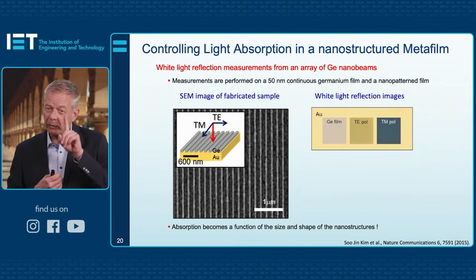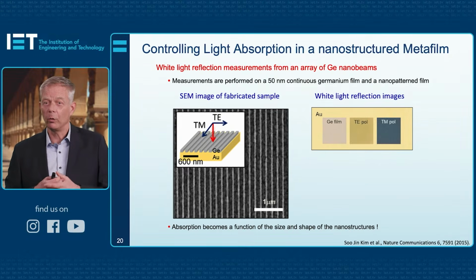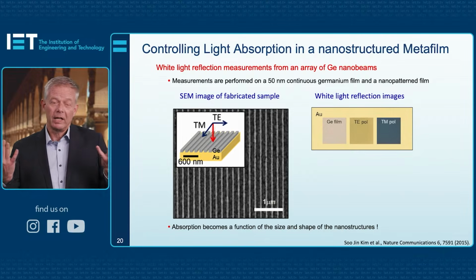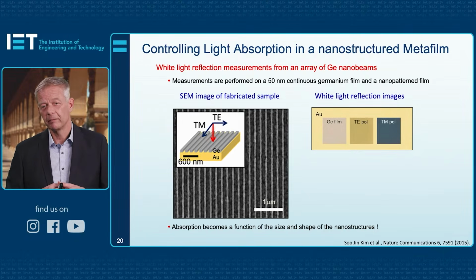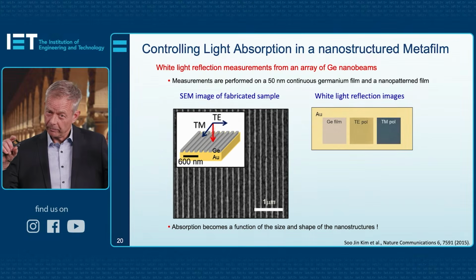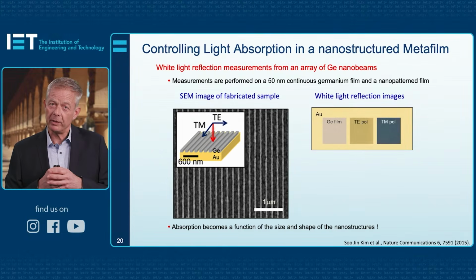But on the right, when we align the electric field along the wires, something spectacular happens. We drive a resonance, and actually the film goes black. So note that in going from the continuous film, by removing about two-thirds of the material, we achieve more absorption. It goes from grayish for the continuous film to black for the nanostructured film.